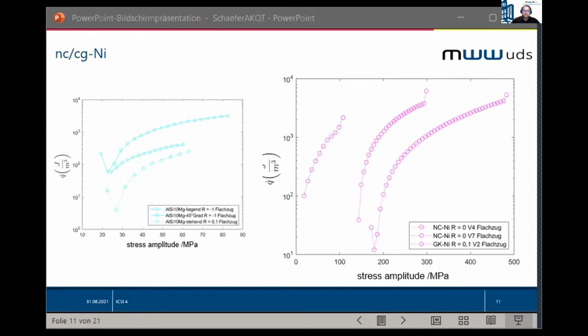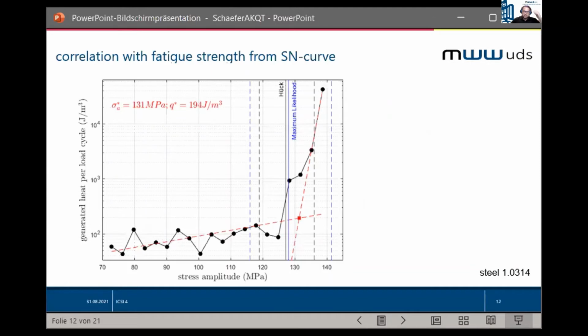But if we consider the nickel samples, we can see that our nanocrystalline nickel from pulse electrodeposition is a very inhomogeneous material. We get very different results for the stress amplitude, and for the coarse grain material, we get a completely different level of the heat generated per load cycle at the knee point. So now we wanted to correlate this knee point with a standard evaluation for the fatigue strength, and we did this for low alloyed steel. And what we found is a very good correlation. You can see here the value from a Hück evaluation, the maximum likelihood evaluation, and here the data from the thermometry, and you can see it correlates quite good.